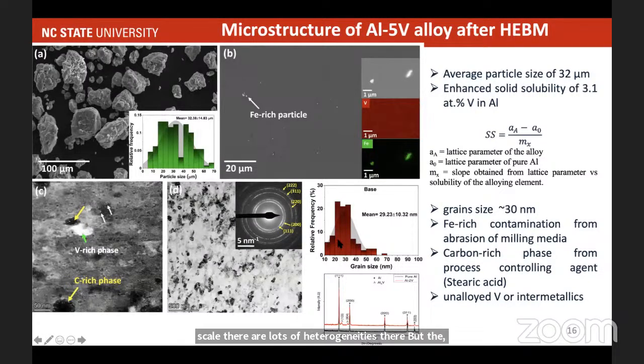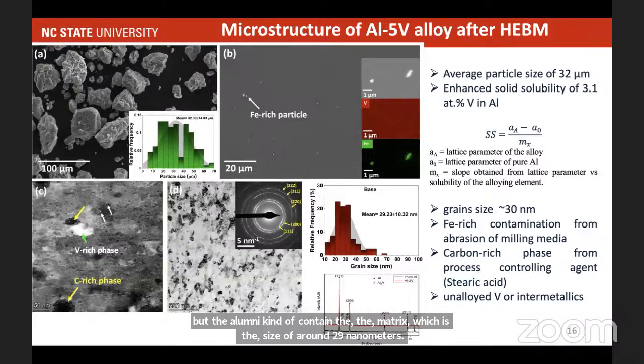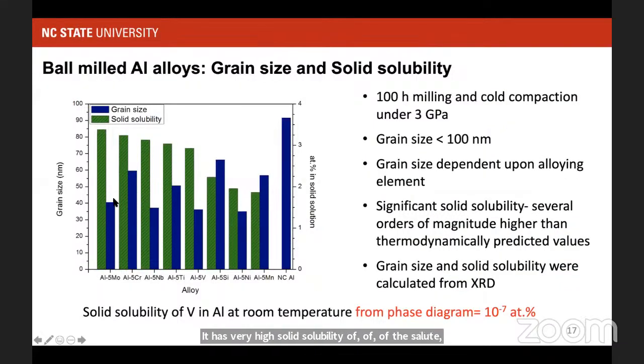But the alloy contained a matrix with a grain size of around 29 nanometers. It has very high solid solubility of vanadium, the solute. We further looked into the grain size of all these different materials and how much solute went into the solid solution. The blue bars on the y-axis show the grain size. The grain size always remains below 100 nanometers and varies depending on what solute we use. The solid solubility of those solutes also varies, but in the case of moly, for example, around 3.7, 3.8% of the added solute was in the solid solution. We added 5 atomic percent, and 3.8% of that is in the solid solution, which is huge because, predicted from the phase diagram, these are insoluble elements. So you have 7, 8 orders of magnitude higher solid solubility.